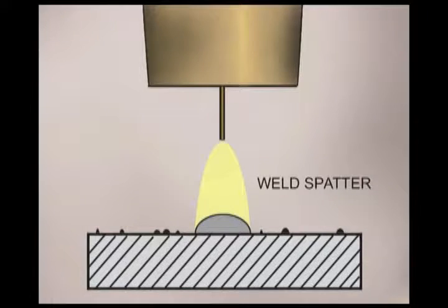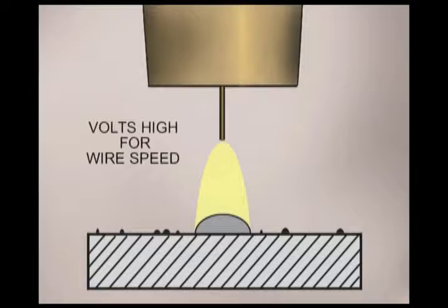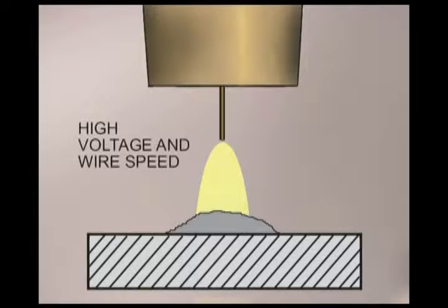When there's excessive weld spatter, the voltage is probably too high for the wire speed. If the weld is kind of flattened out and all over the place, you might be running hotter than you can handle with the wire directed at the back of the puddle. When the finished weld bead has the correct size, shape, and it's fused to the base metal, that's as good as it gets. Well, that's about all there is to the fundamentals of gas metal arc welding.